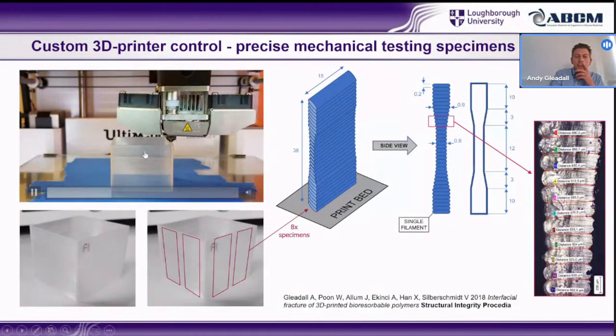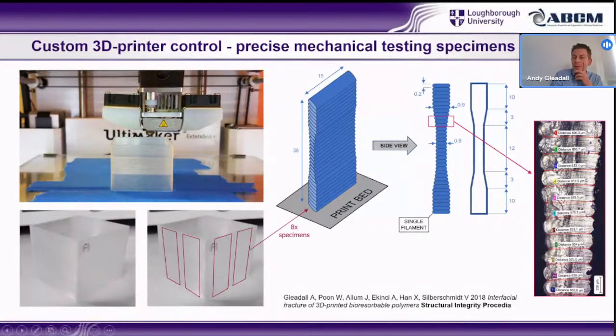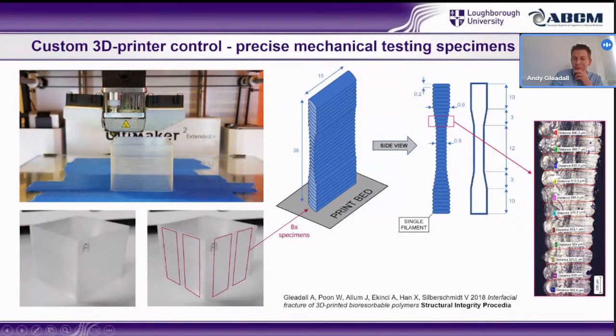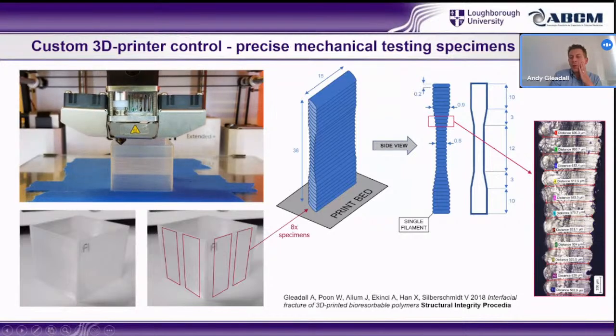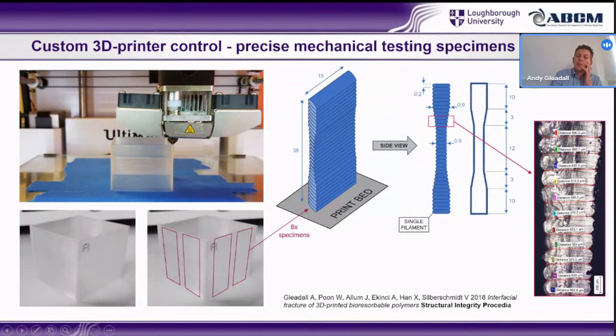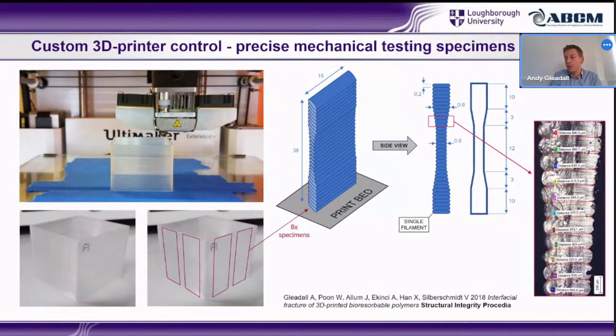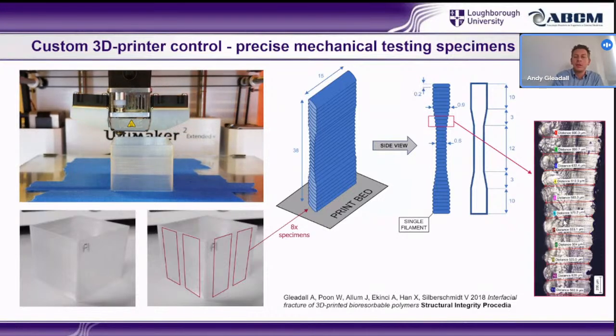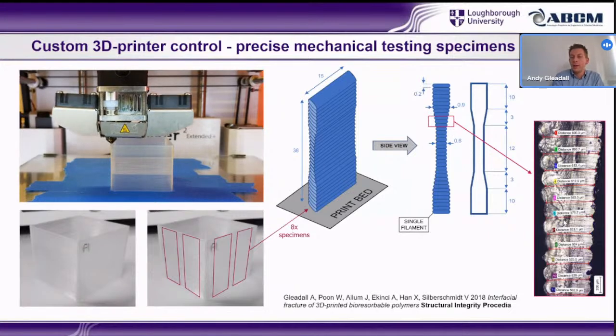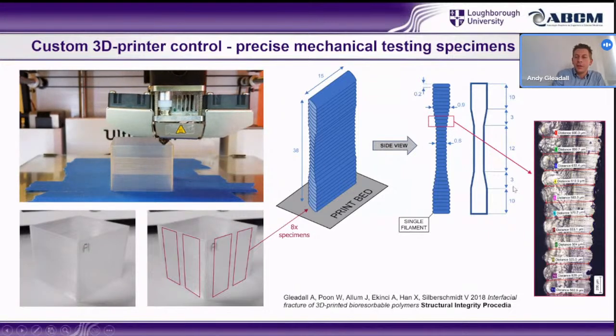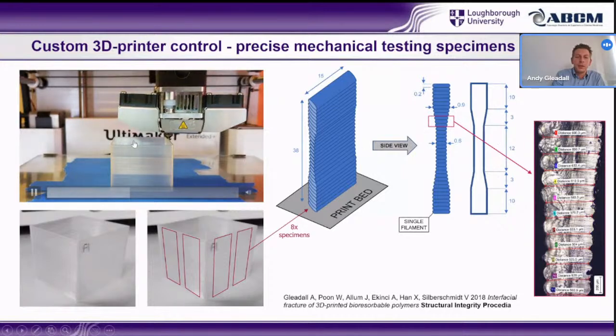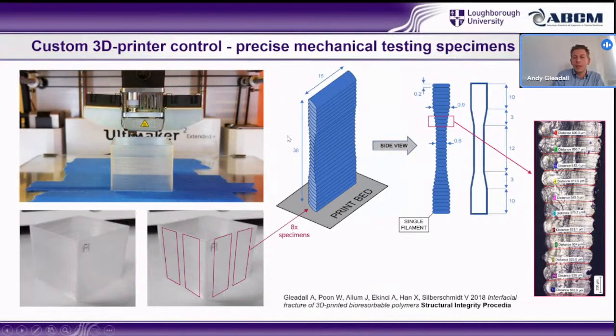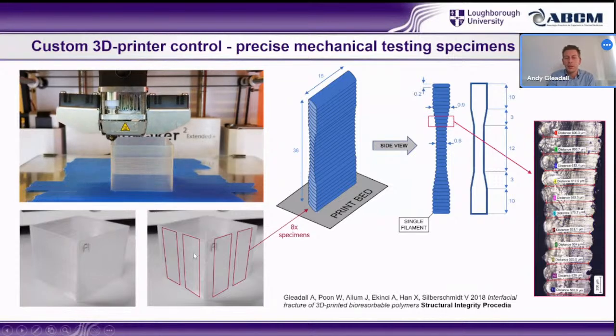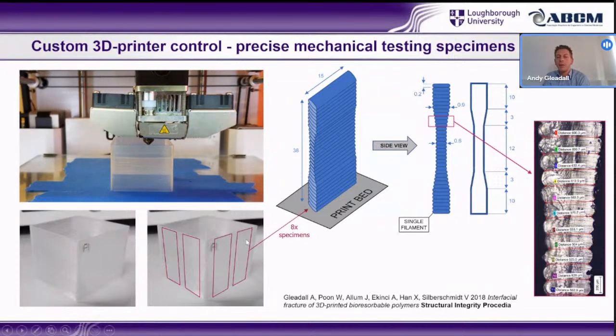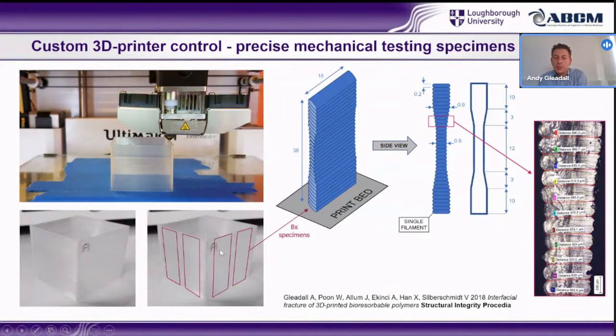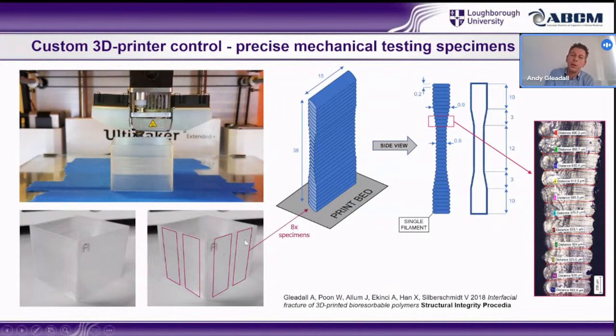So we achieved the dog bone specimen by controlling the width, as I showed in some of the earlier bits. And it seems really simple and logical now, but I remember as we were developing this, first we were thinking we can go from 2 filaments to 1. It was at one point we just suddenly realized, oh, we could transition from wide to narrow, and that would be even better. And it worked really well. We can print these boxes really quickly, get lots of testing specimens by cutting nice rectangular specimens out of the box, which is really advantageous over cutting a dog bone, because we don't need complex dies.